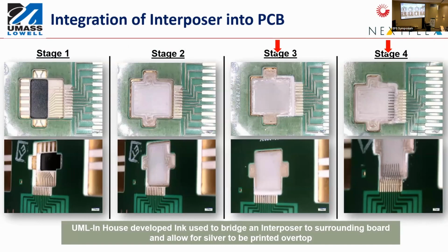Now, in order to test these interposers, we then put them into a printed circuit board. So stage 1, there's no interposer. Stage 2, the interposer goes on. But what you note is then we put the gasket ink around it, because there's spacing around it. And then we have to print the conducting traces over to the interposer, which is what you see here.